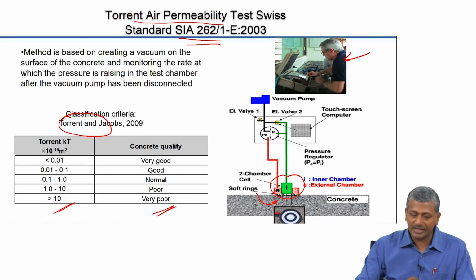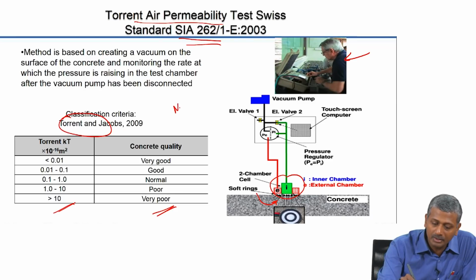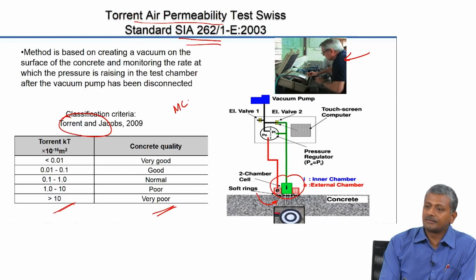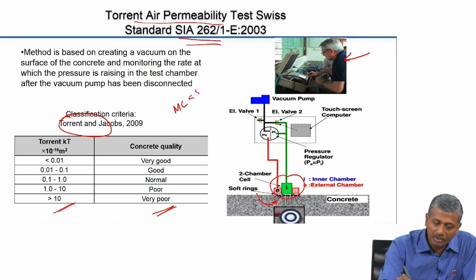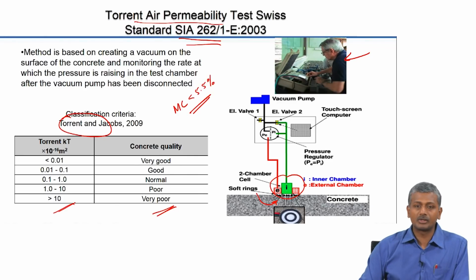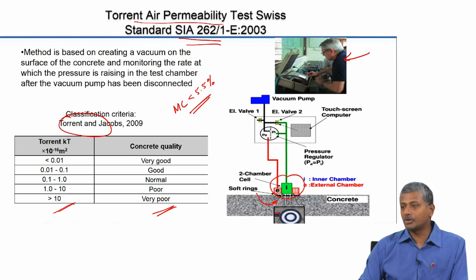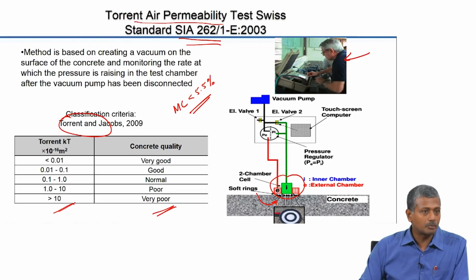So, before you do this test, you need to determine the moisture content of the concrete at the surface, and that should be less than 5.5%. Before you apply this to real structural concrete, you need to ensure that the moisture content in the surface of the concrete is less than 5.5%.